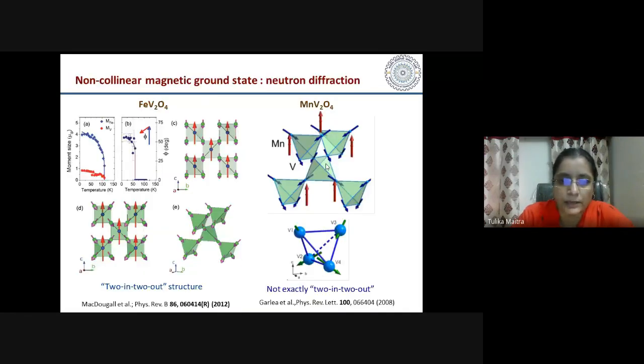Okay, and the non-collinear magnetic state was observed by neutron diffraction experiments, where they see, particularly for FeV2O4, a state which is called 2-in 2-out structure. So it looks like this. And in the MnV2O4 case, there is this non-collinear structure which is not exactly 2-in 2-out, but it is similar. Okay, so these are the non-collinear magnetic ground states that are seen in these compounds from experiment.